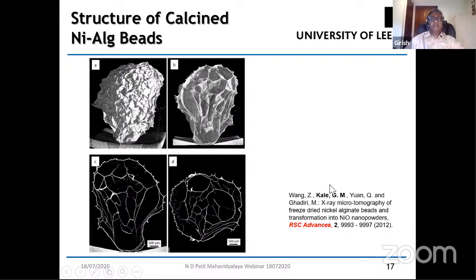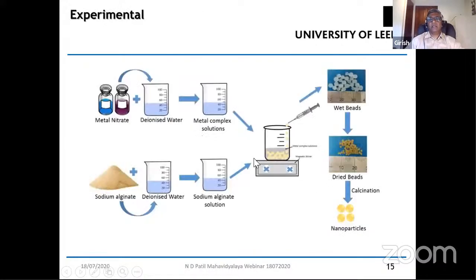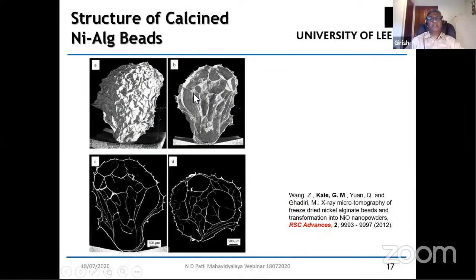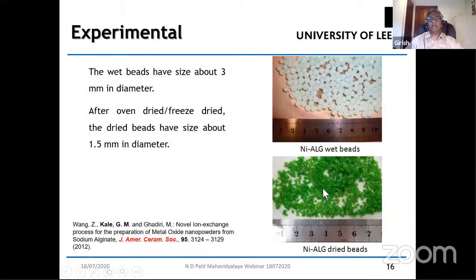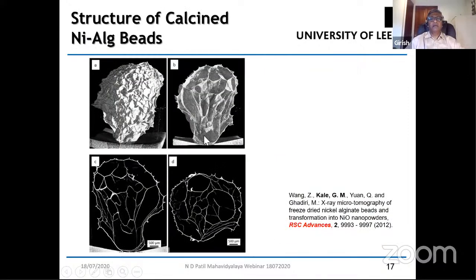We also did some examination of the internal structure of the dried beads. So these are the dried beads, as you see here. We did X-ray microtomography of the nickel alginate dried beads, and what you see is a very porous structure. All these veins are the locations where you have metal ions present, and in between these veins, you have the empty space in the dried beads when the water is gone.